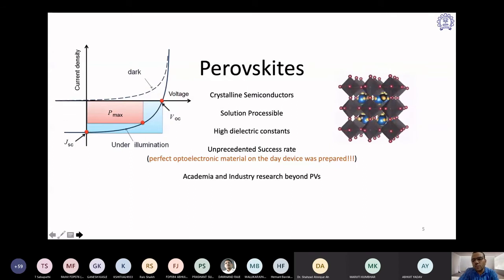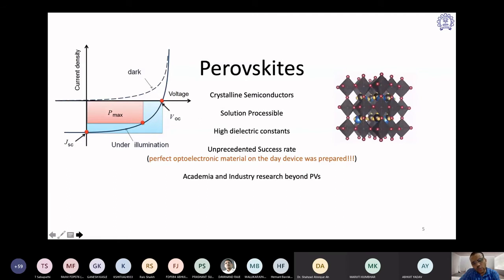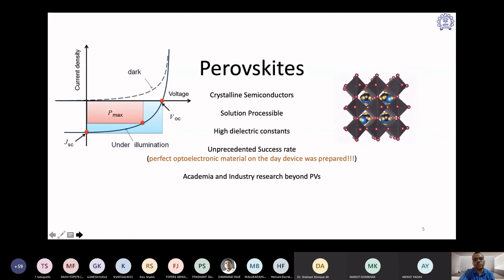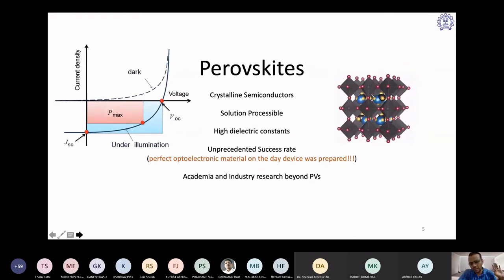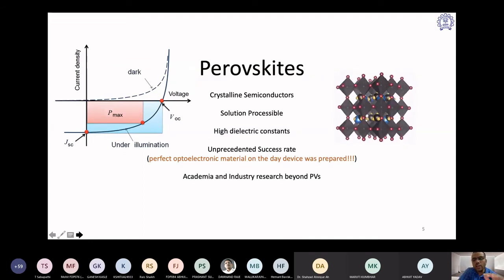So the moment this kind of solar cell is put outside in real field conditions and the temperature goes to 60-70 degrees Celsius in Rajasthan or in Kutch or some of those Andhra Pradesh regions, these solar cells will again fall apart, and you will have your inorganic salt separately and the organic salt already evaporated somewhere, gone somewhere. So these kinds of challenges are there with MAPI, with methylammonium lead iodide.